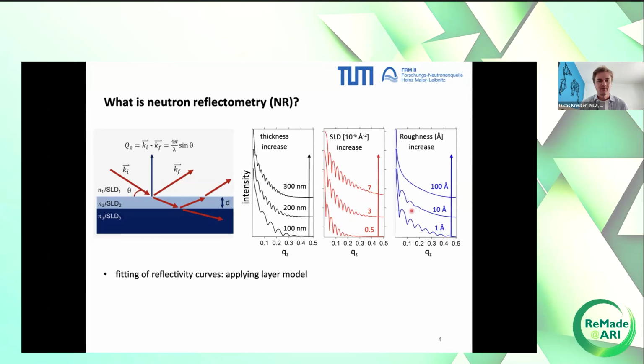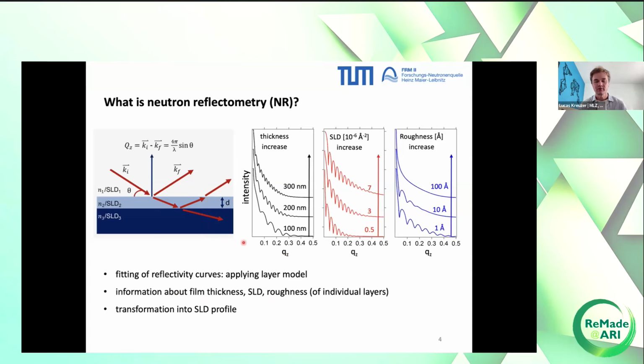Analysis of these films simply works by fitting them. You can apply a layer model similar to these. To this stack here, you can add, of course, a couple more layers, as I said, to simulate gradients or anything in there. And then you get information about film thickness, SLD, and the roughness, not only of the entire stack, but also of your individual layers. And as a bonus, so to say, you can also transform this into an SLD profile, and this I will show you on the next slide. So this is just the basics of neutron reflectometry. If there's still any question, we for sure can address these then in the discussion part.